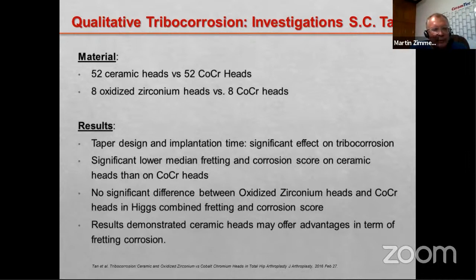For the first group, they found clearly a significant lower median fretting and corrosion score on the ceramic heads than cobalt chrome. In the second group, between zirconium and cobalt chrome, there were no differences between the two groups. Finally, they concluded that using ceramic heads may offer advantages in terms of fretting and corrosion. Let me go now to the second aspect.